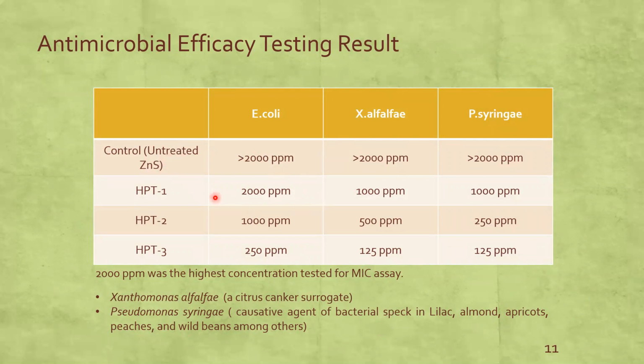So the samples' efficacy differs with different bacterial strains. For example, if we're looking at HPT2, it is not as efficacious in E. coli as in syringae. But we do see the consistent trend that with increasing peroxide concentration, there is better antimicrobial efficacy in all three strains. So this may be due to the conversion of zinc sulfide to zinc sulfate, so there are more available zinc ions for killing.